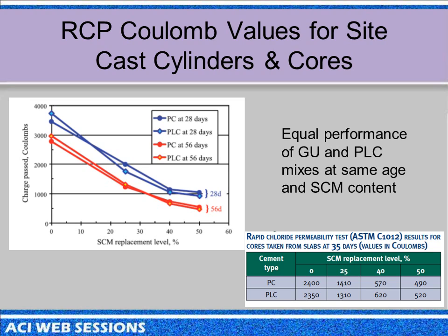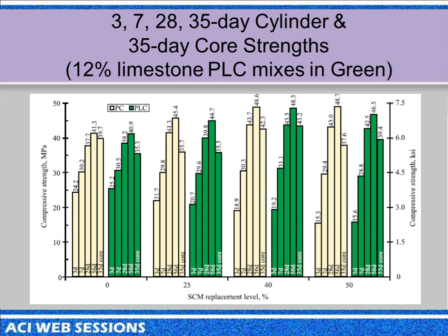So you're seeing the same performance with increasing amounts of SCM replacement of the Portland cement or Portland limestone cement. So we're seeing the same reductions with the pozzolans in this case, regardless of the limestone and regardless of the age. And these are strength results, which of course you can't see. They look like a bunch of bars, but this is the straight cement. The limestone cements are in green with different amounts of SCM replacements, and these strengths are going from 3, 7, 28, 56, and then 35-day cores are on the right.